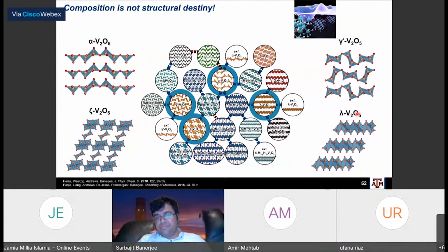The other question on vanadium oxide is, can we have structures other than MxV2O5 that could be used for water splitting? Oh yeah, absolutely. I didn't expand beyond this, but it's a really good question. We have lots of V3O8 structures and VO5 structures. What we're generally looking for is a p-block and a transition metal together that has reasonable band alignment with a quantum dot. This is a vast space, and of course, depending on what sort of quantum dot you pick, you want the quantum dot that gives you the maximum overlap with the solar spectrum, right? Cadmium telluride is good because it is a commercial photovoltaic material, but there are other ones coming. As long as we can match those band gaps with our different oxides, we can be in business in terms of harvesting holes and capturing the solar spectrum effectively.